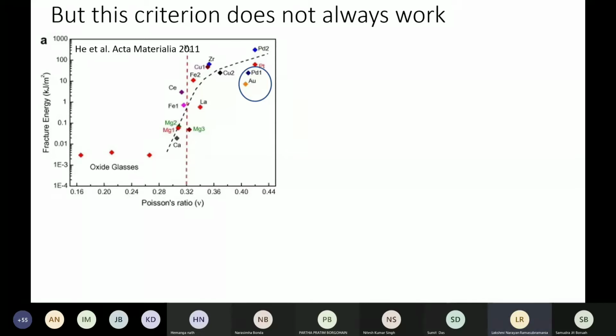So this criterion may not always work, and there is a reason why: you're using an elastic parameter to understand plasticity, which is always a questionable thing to do. So what do we do? As mechanical engineers and materials engineers, we look at a structural perspective. That is most important, because mechanical engineers cannot really use an elastic parameter to define a plastic situation, right? So what we'll do is look at the notch which is about to nucleate a crack. What is the nature of this particular notch?